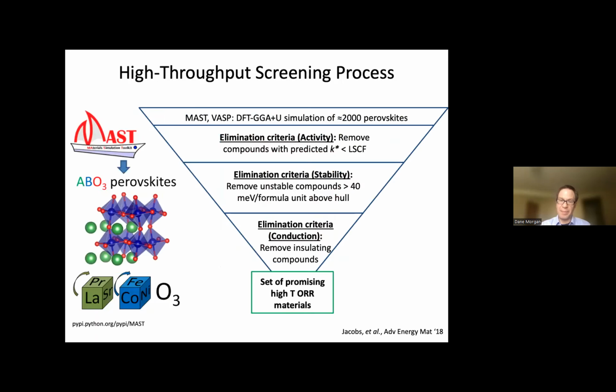So let me show you what happens when we do this kind of screening. You can basically think of it as a big inverse funnel. We set up a big list of automated quantum mechanical calculations. We explored about 2,000 perovskites guided by compositions we thought would be particularly promising. And then we basically looked at the surface exchange coefficient and we said it better be better than lanthanum strontium cobalt iron oxide, because that's a commercialized material. If our performance is worse than that, no one's going to be interested.